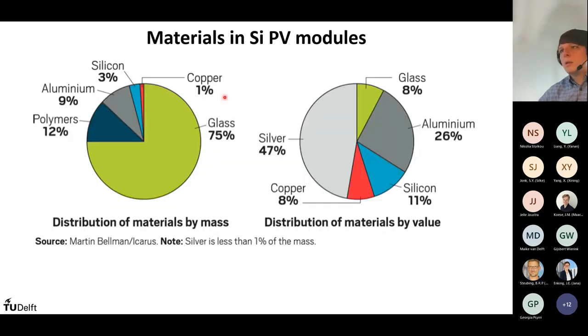So now let's look at the mass. On the left hand side, you see the PV module distribution by mass. And what I already said, about 70 to 75% of the PV module's weight is glass. And then you have the polymers, and about 10% is the aluminum frame. And just 3% are the cells themselves. And 1% is the external copper cables. And a PV module today, in terms of handling, is about 2 square meters large, and it weighs between 20 and 27 kilograms. So it's quite heavy.